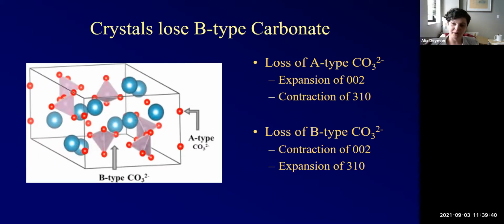Carbonate can go into carbonated apatite in 2 separate ways. The first is A-type carbonate, and that's when carbonate substitutes for OH groups. So you're putting in a big moiety instead of a little guy. The other is B-type carbonate, and that's when it kicks out a phosphate, so a big ionic group, and replaces it with the carbonate, which is a smaller ionic group.